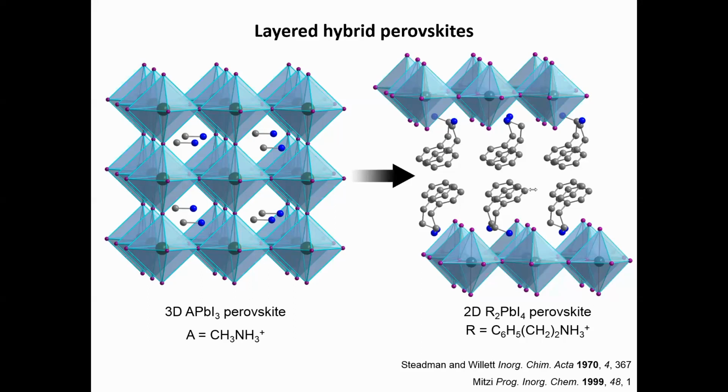But yeah, once there is a published prep, that's kind of the beauty of self-assembly. And you can also even deposit films. Yes. You just take the precursor solution, you just drop it onto a substrate, and then when the solvent evaporates, you form a film. And what's really nice is with these layered materials, the layers are parallel to the substrate.